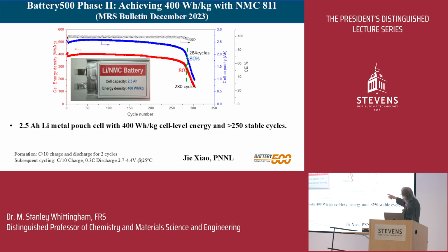So here we're at 400 watt-hours per kilogram. We're getting about 250, 300 cycles. And we have, in fact, most recently got up to 500 watt-hours per kilogram, our original goal. We got about 60 or 70 cycles. But in all these cases, now we have to improve each component and make sure the system is safe.